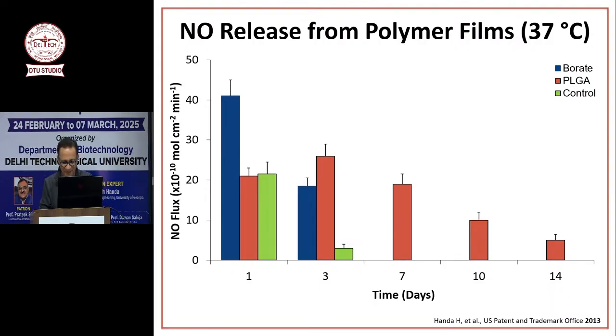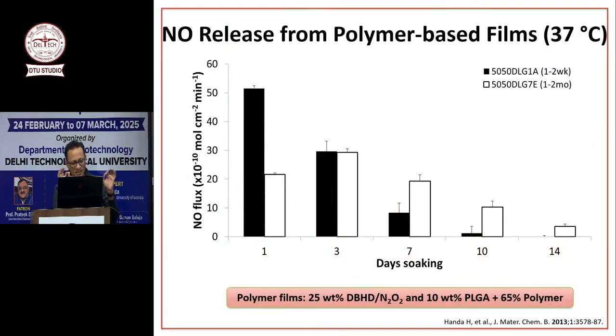So what we did is, we got different types of PLGA. A very fast degrading PLGA and a very slow degrading PLGA. 1 to 2 week degradation and 1 to 2 month degradation. And when we did NO release, this is interesting now. You have to pay a little bit of attention. Black is 1 to 2 week degradation PLGA. So that means it's degrading very fast. That means it's creating a very acidic environment in the coating. That's why the release is so fast on day 1. But it's dead by day 10, because you released all your diazeniumdiolates very fast, NO release very fast, and it died quickly.